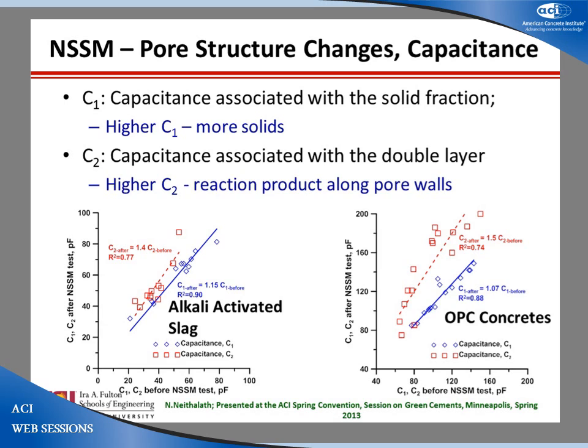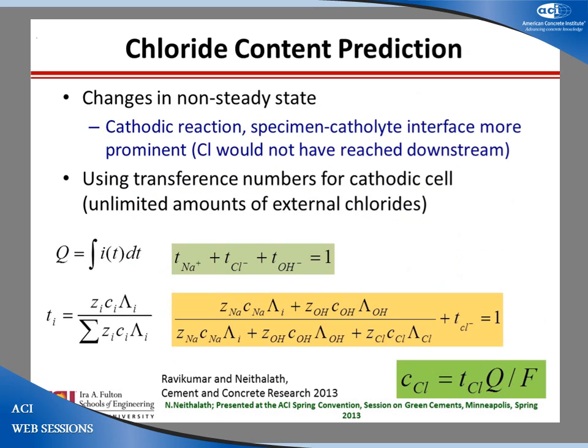Exactly like, if I may say, silica fume concretes. But non-steady state migration, which is 24 hours, gives you a much better indication of what's happening in the pore structure, at least from a point of view of comparison with OPC and alkali activated slag. You can see much more similar behavioral trends when you look at the microstructure and how that changes with time.